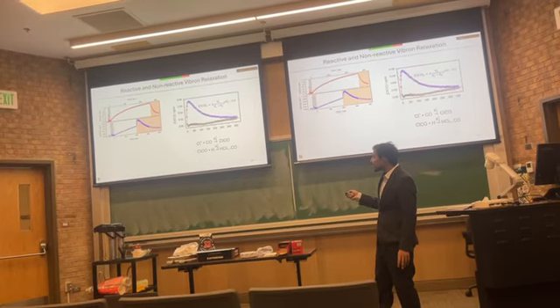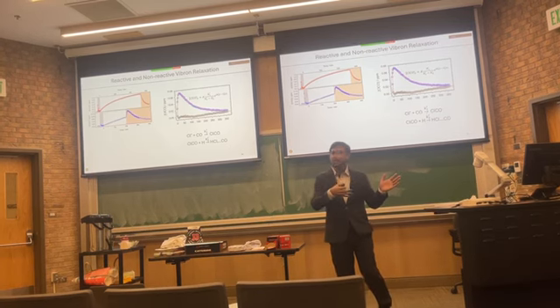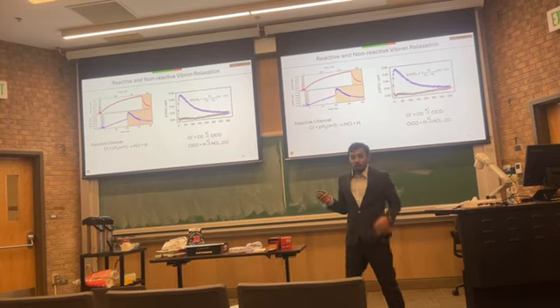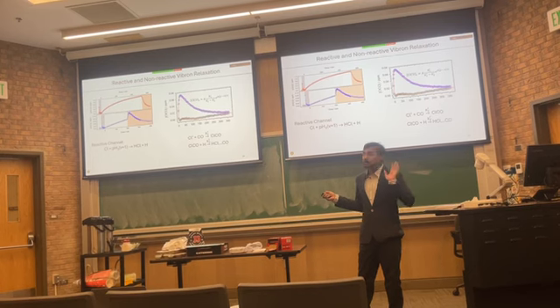So you have a reaction where ClCO is being produced, and another reaction where ClCO is breaking, because we know that with near infrared, it will break. So it was breaking to HClCO. So what we think now, having studied this reaction for a long time, since 2006, is that the chlorine atom will react